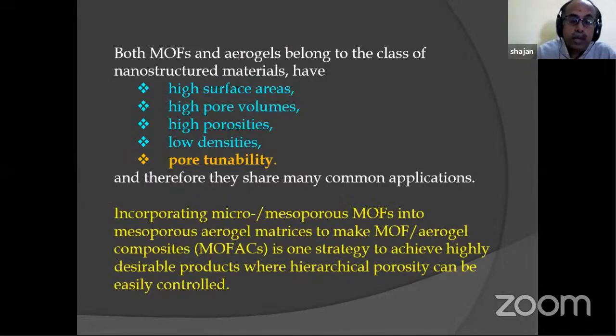So incorporating a microporous and a mesoporous material, where the microporous is a MOF and the mesoporous is an aerogel. So when we combine these two, we get a new material, and that is what you call MOF aerogel composites, abbreviated as MOFACs. And that is being widely experimented all over the world.